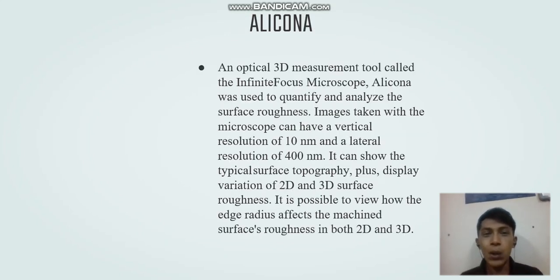So for the Alicona, it is an optical 3D measurement tool called the infinite focus microscope. Alicona was used to quantify and analyze the surface roughness. Then when we use the microscope, it will capture the image with a vertical resolution of 10 and a lateral resolution of 400. It can show the typical surface topography plus display variation of 2D and 3D surface roughness. Thus, it is possible to view how the edge radius affects the machined surface roughness in both 2D and 3D.